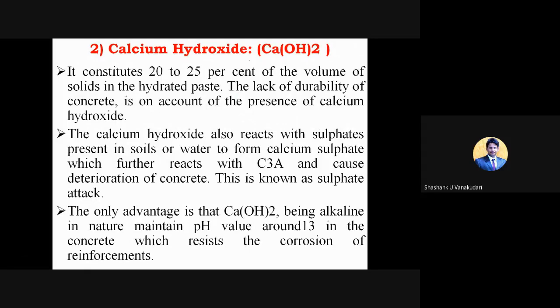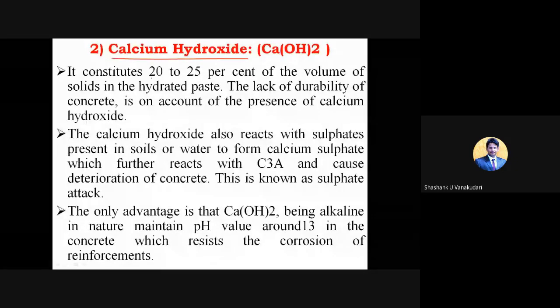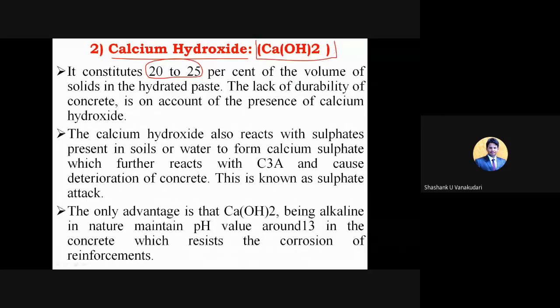Okay, so calcium hydroxide, that is Ca(OH)2. This constitutes around 20 to 25% of the volume of solids in the hydrated paste. Once the cement reacts with the water, it forms a certain paste, and that paste consists of calcium hydroxide also. That calcium hydroxide will be there in this percentage, 20 to 25% of the total volume of solids. And the lack of durability of the concrete is on account of the presence of calcium hydroxide. You can see the cracks present in concrete structures. Those cracks are because of various aspects. If the reason is the concrete itself, then the presence of this calcium hydroxide will be the main reason for the durability problem.